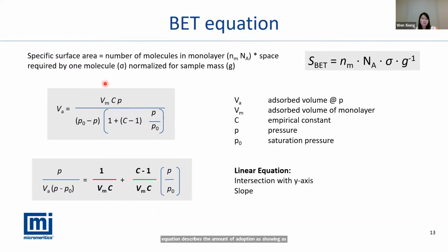Then we can transform this equation to the linear form by knowing the adsorption volume at the relative pressure from our analyzed data, which is our gas adsorption isotherm. The monolayer capacity and the C constant can be calculated from this equation, from the y-intercept and the slope of the fitting data in this linear form.